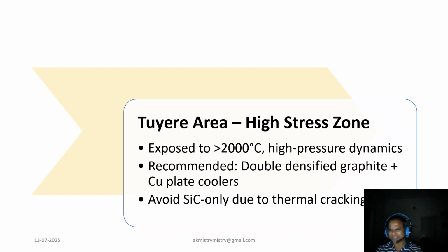Now coming to the tuyere area, which is a very high stress zone. The tuyere zone is just like a pressure cooker of the furnace. Temperatures breach 2000 and even more, and dynamic loads vary rapidly, instantaneously, spontaneously. Hence, double densified graphite plus copper plate coolers provide unmatched resilience. Silicon carbide, although robust, must be avoided in isolation. It's prone to cracking under thermal shocks. The right combination safeguards both equipment and campaign life.